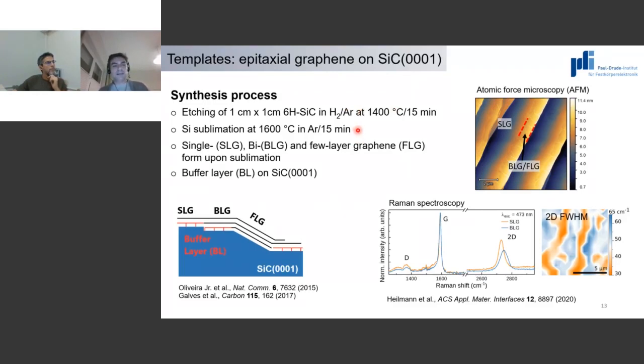And what happens in this case is that silicon sublimates, silicon leaves the surface. In a few words, what is left behind is graphene. So carbon is left behind. It reconstructs and forms a very nice epitaxially aligned graphene layer. Is that pure single layer graphene?